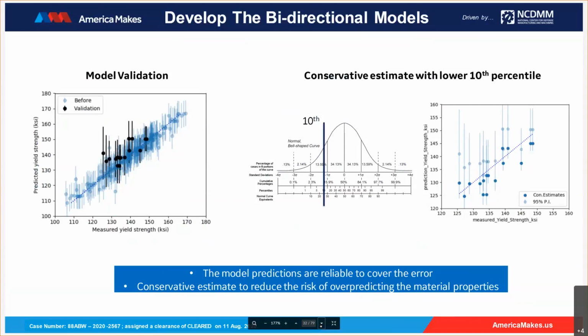For example, at the leftmost point, the black dot, the prediction is around 140 ksi. The measurement is actually about 125 ksi. And even for this case, where we got about a 10% error, our BHM model can still identify the larger error with a larger error bar, and the error bar can still cover the prediction error.